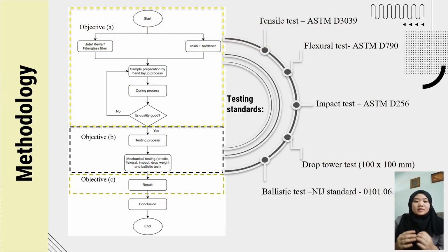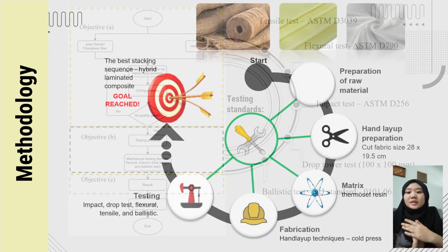As you can see, here is the flowchart of the methodology. There are some tests that are required in this research, which are tensile tests, for which we use the ASTM standard D3039, and the flexural testing, for which we use ASTM D790. For the impact test we use ASTM D256, and for the drop tower test we cut it into 100 times 100 millimeter panels, and for the ballistic test we use the NIJ standard 0101.06.